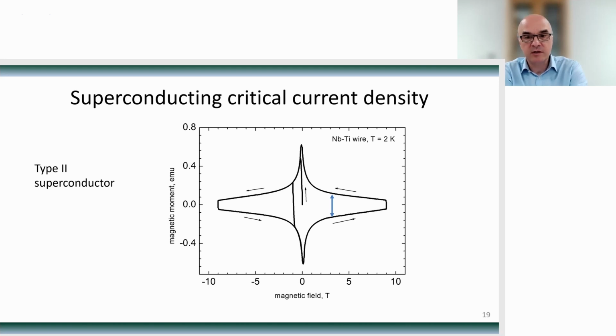Drifts, that is a great question. And in some instances, we did have to think long and hard about how to avoid drifts or mitigate them, as you say. For the VSM, the drift problem is not that important, I should say. The best technical way of mitigating the drifts is first to make sure that what we measure is a direct measurement of the sample environment. We have a thermometer which is very close to the sample. So whatever temperature drifts may occur far away from the sample do not affect our measurement.